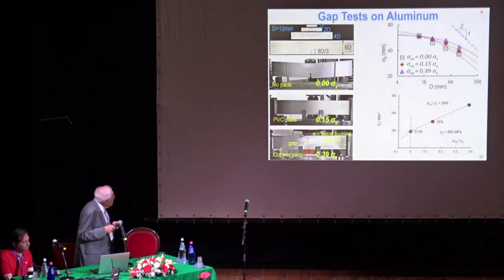Another set of tests, these are the tests of aluminum. So here's the logarithm of nominal strength, the logarithm of the size. You see beautifully the size effect curve. In fact, aluminum has very little scatter, so it's very consistent, as you see.